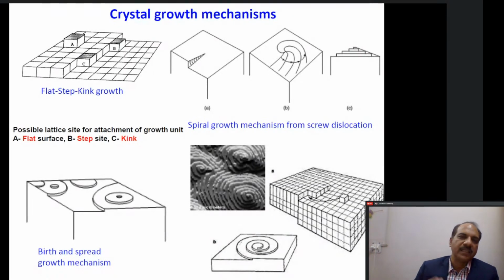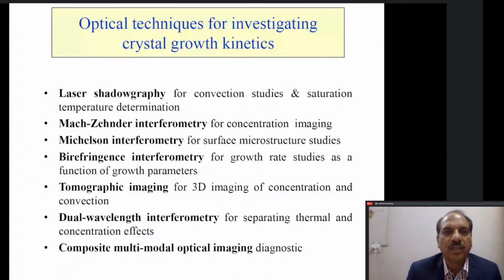So we use several optical techniques, and these are some of them. Optical techniques for investigating crystal growth kinetics: laser shadowgraphy, for convection studies and saturation temperature determination; Mach-Zehnder interferometry for concentration imaging of the solution from which the crystal is growing, and also the quality of the crystal. I will show you some interferograms of the crystal when it is growing. Michelson interferometry for surface microstructure studies. Birefringence interferometry for growth rate studies as a function of growth parameter. Tomographic imaging of concentration and convection. Dual wavelength interferometry for thermal and other effects. And then finally all these techniques have been integrated into a single setup which we now use, and we call it a composite multimodal imaging technique.